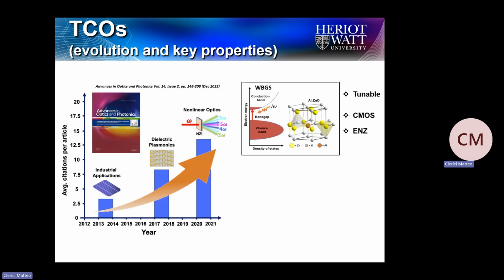However, soon after these studies, we realized that when these materials are operated in the near IR spectral window, where the refractive index is particularly low, the optical nonlinearities, so our capability to modulate the optical properties of the material represented by the complex permittivity, are extremely amplified. And this is not just related to the magnitude of the effects that we can record, but it is also related to the speed at which these effects can be recorded. So the nonlinear bandwidth is absolutely outstanding.